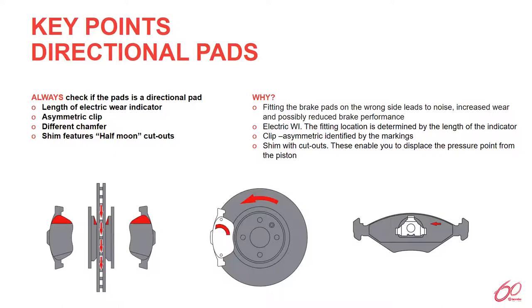And this needs to be fitted with the crescent opposing the direction of rotation, as you can see here on this slide. So if the chamfered pads and the shim cutouts are fitted in the wrong direction, this will position that pad incorrectly. And rather than prevent NVH, it will increase it. And if not corrected in the long run, this can actually cause damage to the parts.